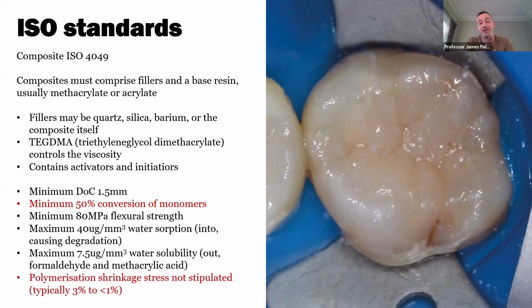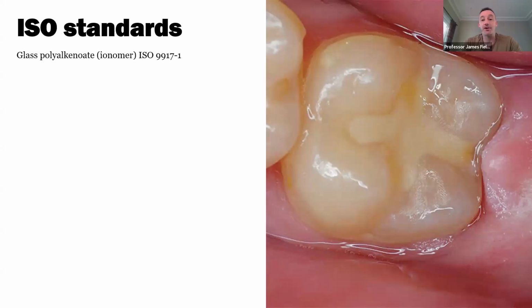Interestingly, for me, maybe for you as well, one of the issues that we have with curing composites is the polymerization shrinkage that happens with them, and the stress that might apply to the walls of a cavity as the composite cures. That is actually not stipulated in the ISO standards. And again, perhaps another reason why these standards should be updated, because nowadays we do want some indication of how much stress might be caused on polymerization, and it would be a good idea to minimize that and to have a certain maximum in the standards. So again, just a little bit of insight there into what composites need to do before we go any further. And finally, the glass ionomers, the glass polyalkenoate cements, have their own standard as well.